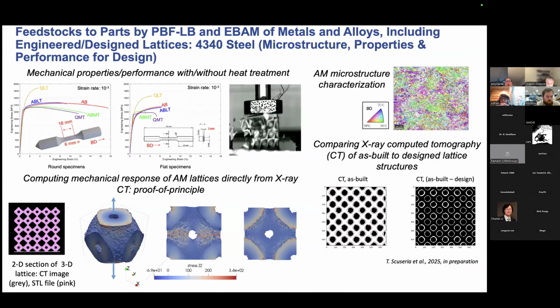Adapting that kind of modeling to EBAM scenarios and wire-based scenarios is another thing that we're doing at the moment. And then I would say also taking that to feedstocks to parts, especially for these designed and engineered lattice structures. So this is an example of mechanical properties and performance, both with and without heat treatment. And here we're comparing, for example, round specimens versus flat specimens. And it's interesting that you do see a difference.